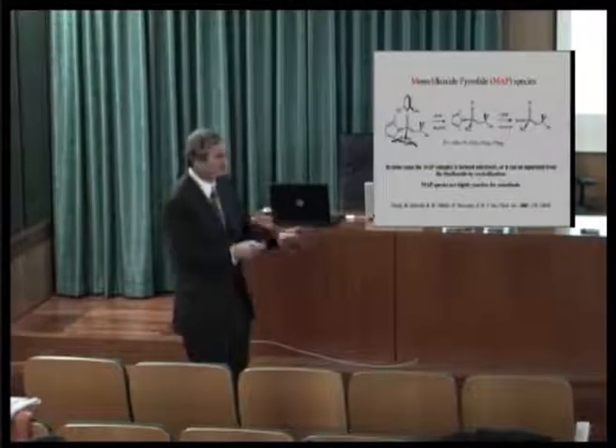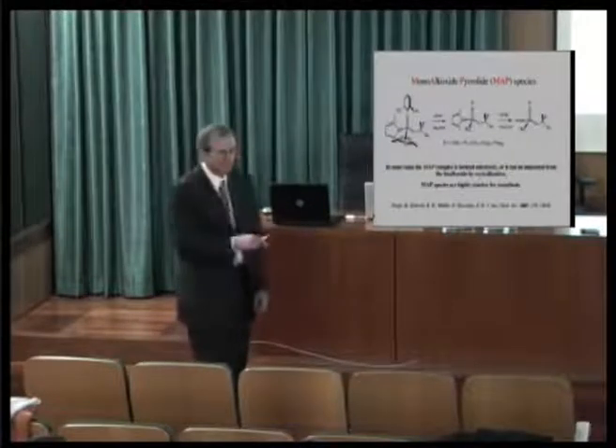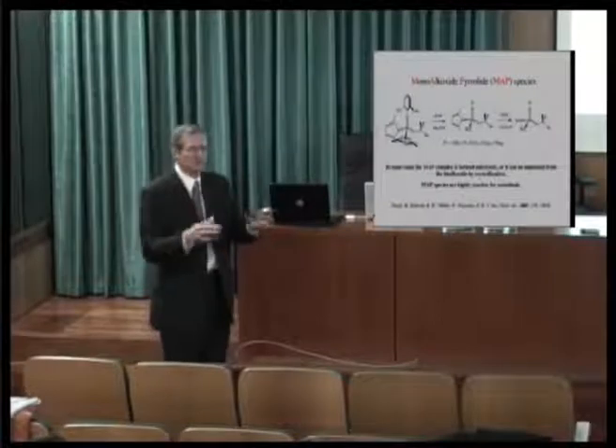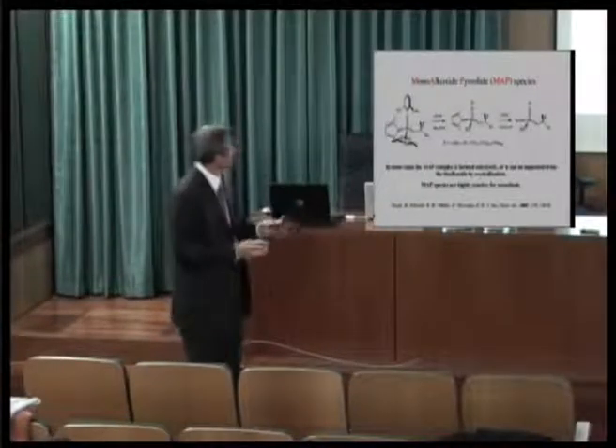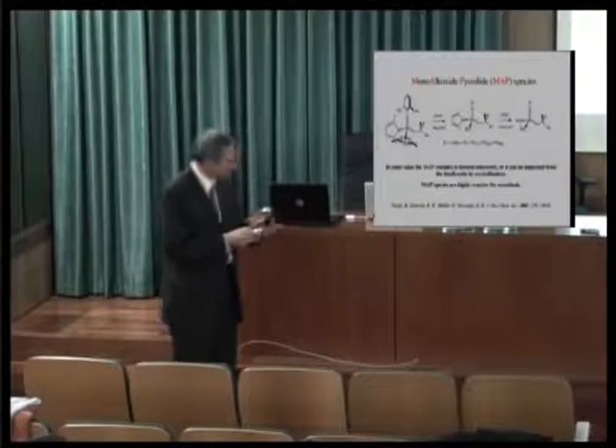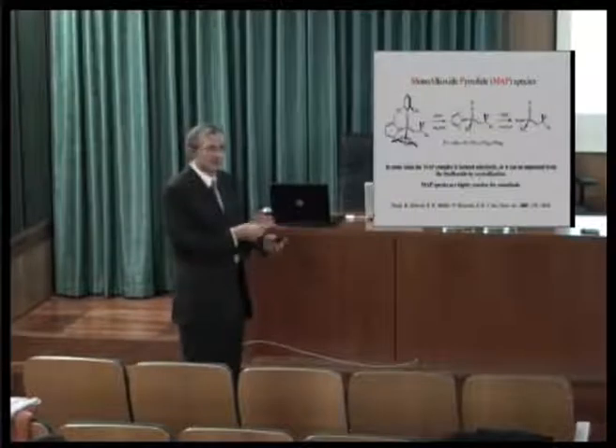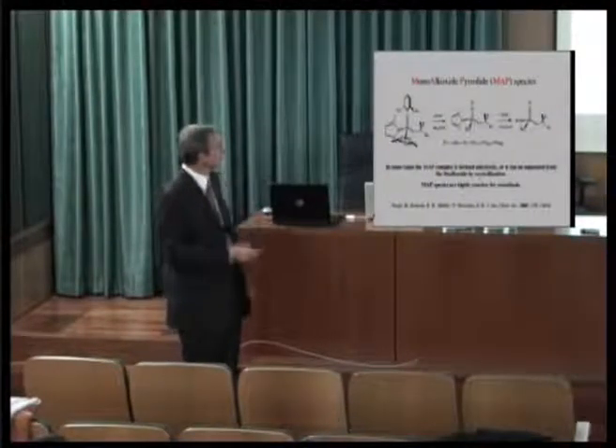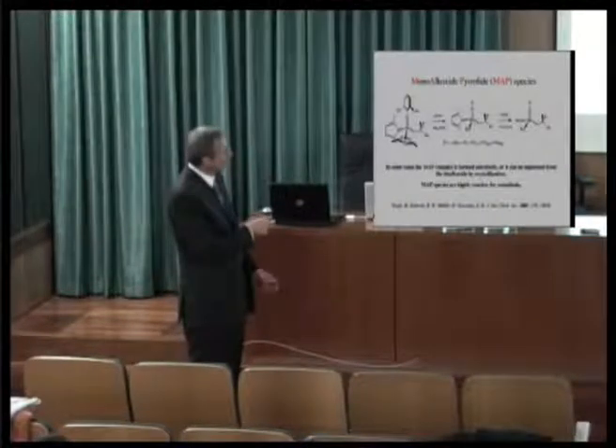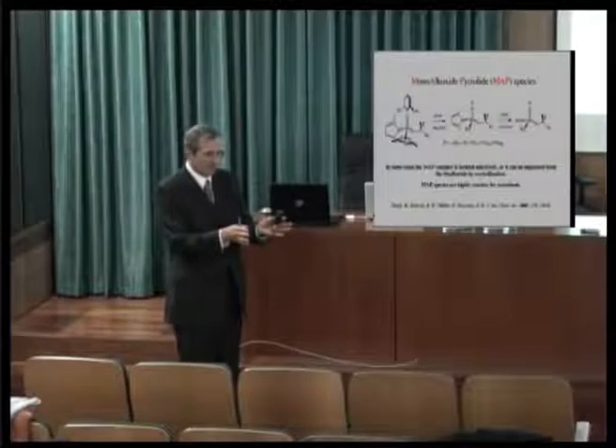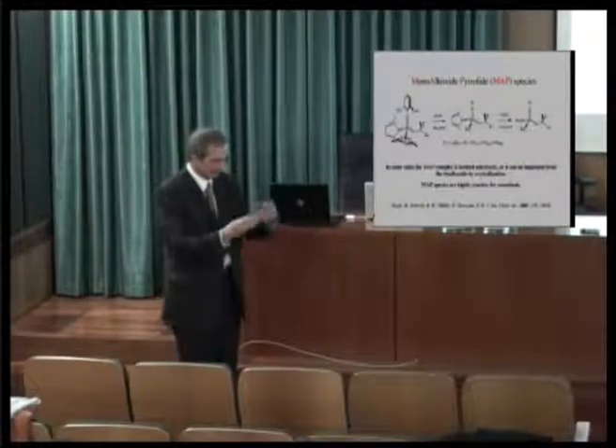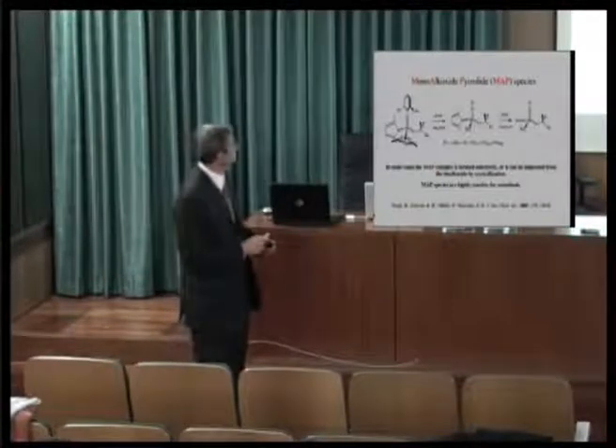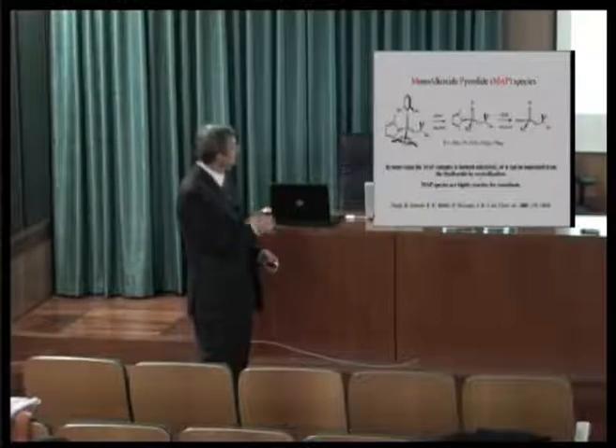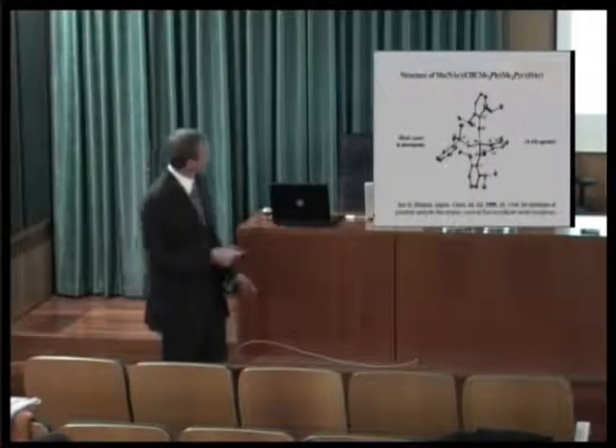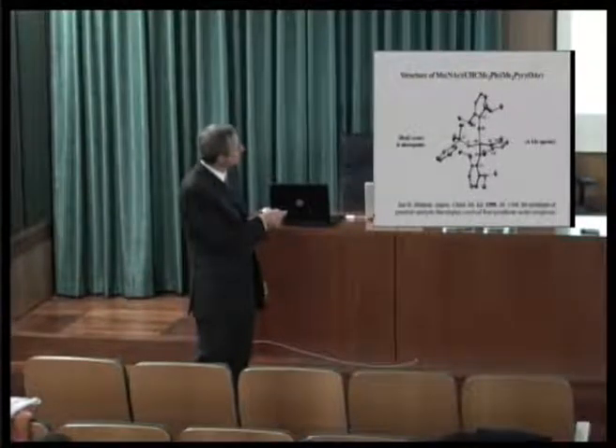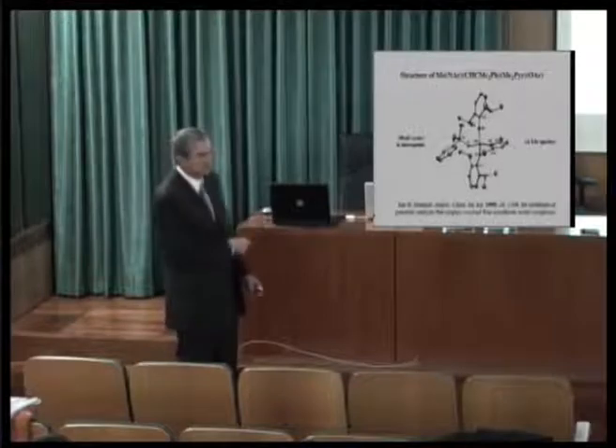One possibility among many is that the metal itself is unsymmetric. It's the chiral center. That's not new in organometallic chemistry and inorganic chemistry, but it is unusual for a catalyst itself to have an unsymmetric center, and it, as you'll see, is really a very important feature of the catalytic reaction. And the fact that all the intermediates are not symmetric in some way, but distorted, is perhaps why they turn over, the catalyst turns over rapidly. So these are very highly reactive, these MAP species. The structures are not unusual. The pyrrolide is bound only through the nitrogen. So these are 14 electron species as we count them.